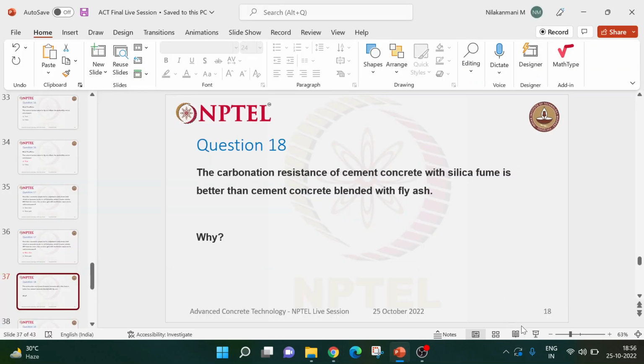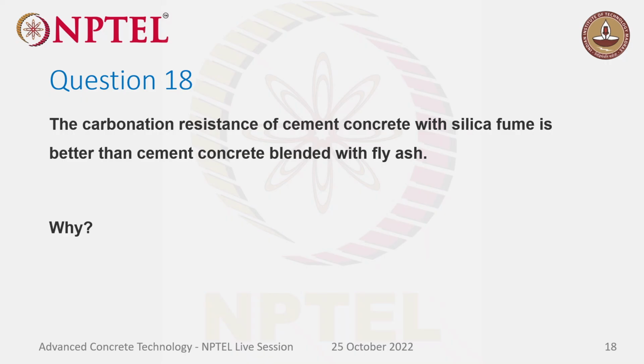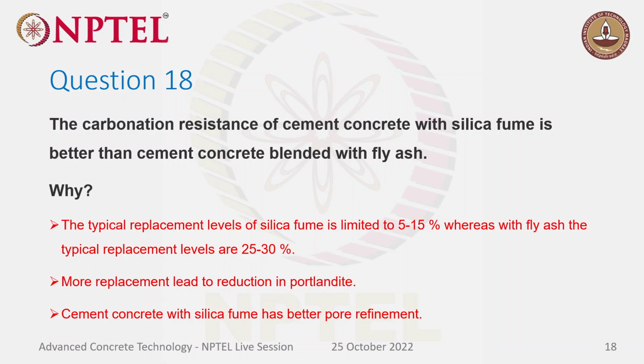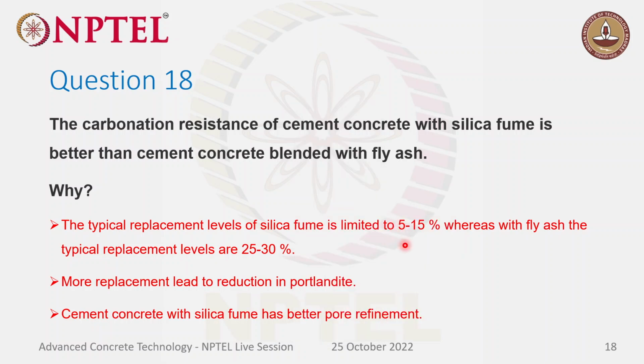Now let's see what are the reasons that can contribute to carbonation resistance of cement concrete with silica fume when compared to other blended systems. Let's see why. The typical replacement level of silica fume is limited to 5 to 15%. Mostly it's 10% in most of the cases. Whereas with fly ash, the typical replacement levels are 25 to 30%. More replacement leads to a reduction in the Portlandite content available. So if more fly ash is replaced, it will consume all the Portlandite, right?